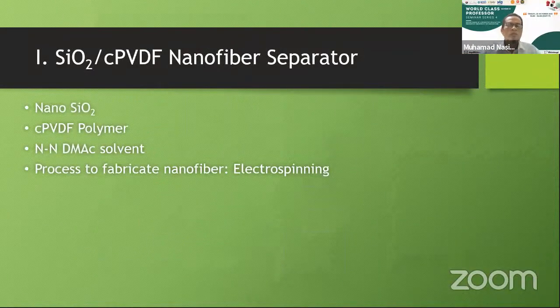Okay, now we try to make a separator based on silica and co-PVDF nanofiber. As we know, we can control the thermal stability of the composite by adding the silica. And we also use co-PVDF polymer because it has good physical and chemical stability. And we use N-N DMAc solvent. And then we produce the separator by using the electrospinning process.